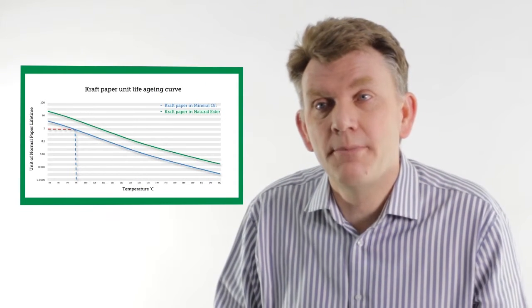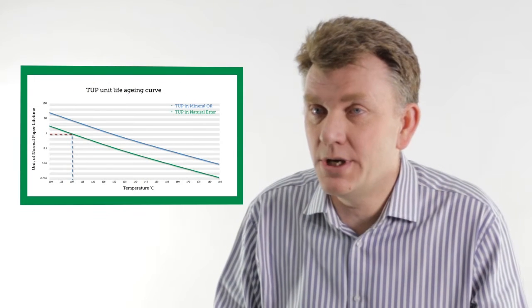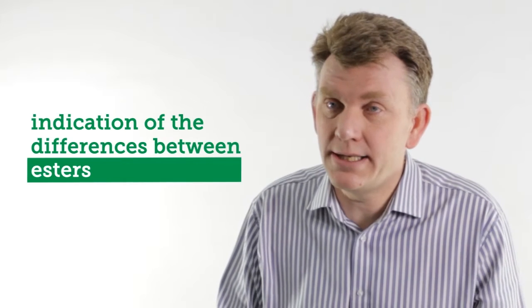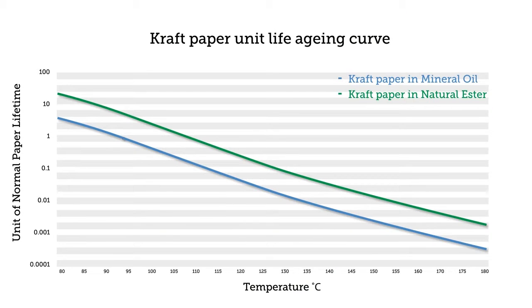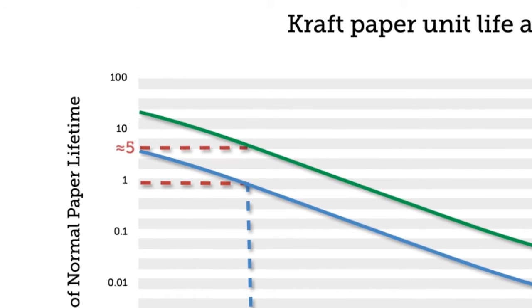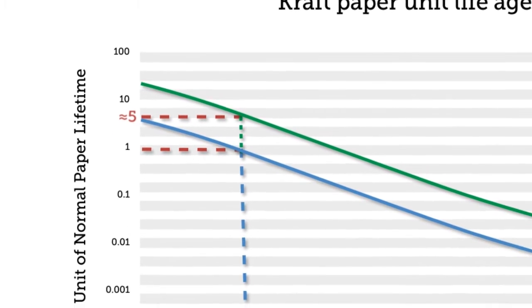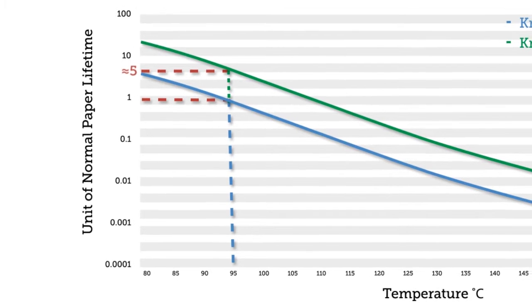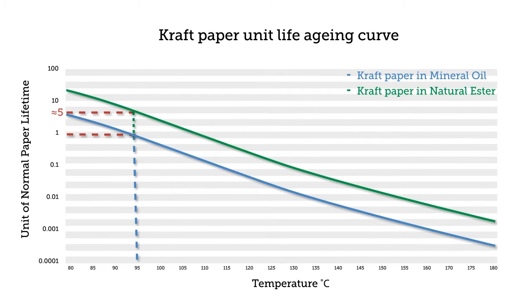The IEC and IEEE have summarised the paper aging benefits of esters in their recently published standards regarding high temperature insulating materials. In these standards, the unit life paper aging curves based on kraft paper and thermally upgraded paper give an indication of the differences between esters and mineral oils. To take the kraft paper example, if ester fluids were used, the life of the cellulose would be approximately 5 times longer than if mineral oil had been used at an operating temperature of 95 degrees. Alternatively, the transformer can be run approximately 16 degrees hotter with ester for the same life.